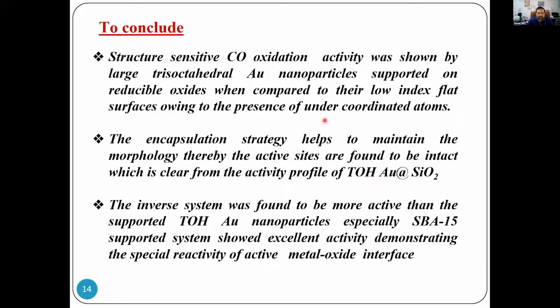So to conclude this particular section of this presentation, I just wanted to tell you that CO oxidation on gold is structure sensitive. If you make a structure sensitive gold nanoparticle, even if the size is very high, you can have reasonably good activity demonstrated from the surface.